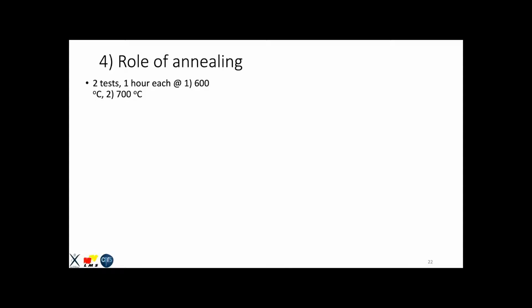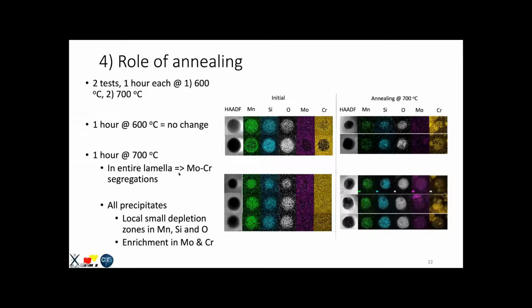We did 2 tests for 1 hour each at 600 degrees Celsius and 700 degrees Celsius. So the 1 hour at 600 degrees Celsius brought no change at all. The 1 hour at 700 degrees Celsius brought significant changes. In fact, in the entire lamella, there was a redistribution of molybdenum and chromium, which was inside those cellular solidification walls. It now redistributed into some very random microsegregations. All precipitates were showing small depletion zones in manganese, silicon, and oxygen. And there was an enrichment in molybdenum and chromium in general. So that was an interesting aspect of annealing, that it's trying to heal the material somehow by removing these heterogeneities. But because it's a thin lamella, it's creating these weird structures. So here, I think it must be an artifact of this thin lamella.